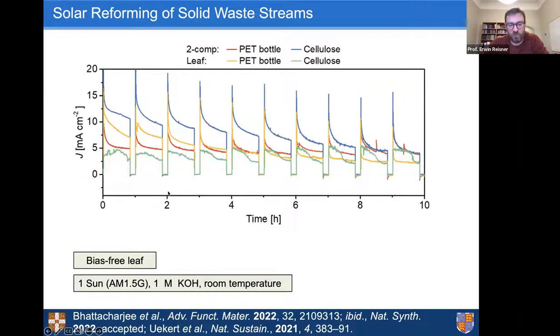And here's also just some of the data. All I want to show here really is two things. First of all, we are not bound to 0.12 or 0.7 milliamps per square centimeter anymore. Even in our first systems, we jumped straight to about 10 milliamps per square centimeter, simply because the chemistry is now so much easier. We do not need the limiting bismuth vanadate anymore, and we can really use a lot of the light and use this to drive the catalysis and chemical transformation.